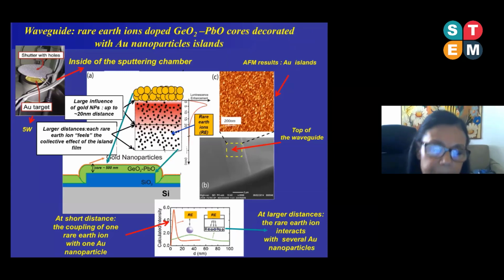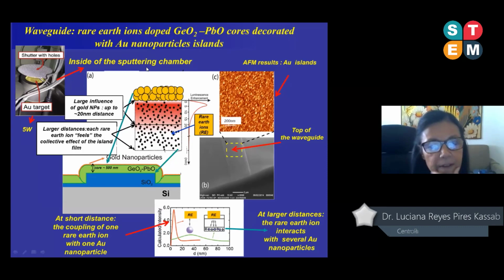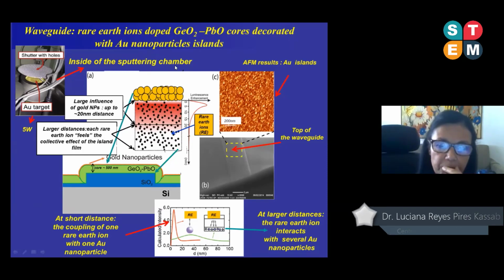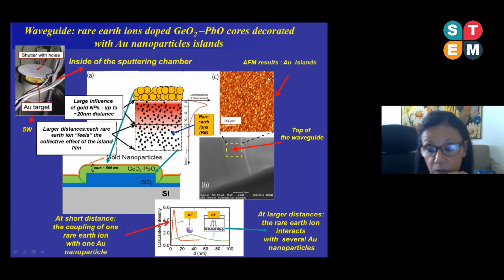But regarding the production of the island formed by gold nanoparticles, as I said before, the island of gold is performed using the sputtering technique. So we deposit gold on the top of the waveguide. However, some special points deserve attention here.